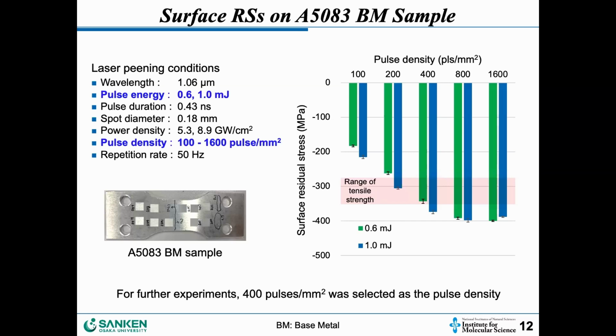So you can see 400 pulses is enough to induce a compressive residual stress on the surface, by comparing this one. The tensile strength is about 275 to 350 around here. So 400 pulses is enough to induce compressive residual stress in the surface. For the further experiment, we use 400 pulses per square millimeter.